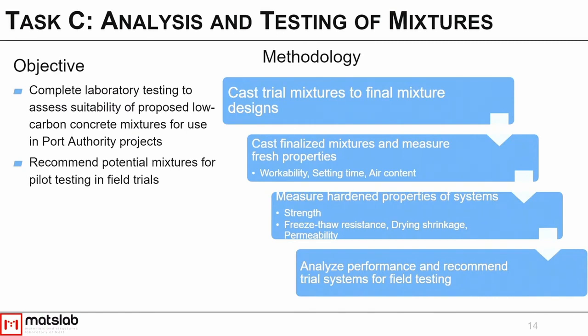And this actually ended up being quite a bit of concrete. We cast probably around 20 cubic feet of concrete in the lab for each one of our mixtures. And when you have a concrete mixer that can only mix about 3 cubic feet at a time, this is actually a lot of concrete made in our lab. So just an example of some of how we did our analysis in terms of how systems performed.